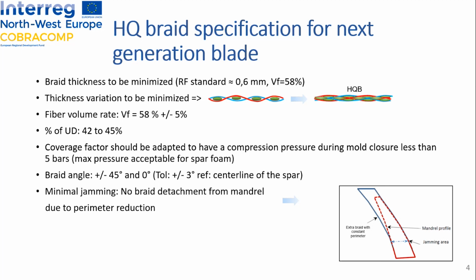We have also to play with the cover factor of the braid because these braid reinforcements will be injected in a mold, and we have to close this mold, but we cannot apply too much pressure on this mold because of the mechanical resistance of the spar foam. That means the cover factor has to be adapted to apply a maximum pressure of 5 bars during the close molding. The braid angle is fixed at plus and minus 45 with unidirectional yarns too. And lastly, we have to minimize the braid detachment from the mandrel due to perimeter reduction.